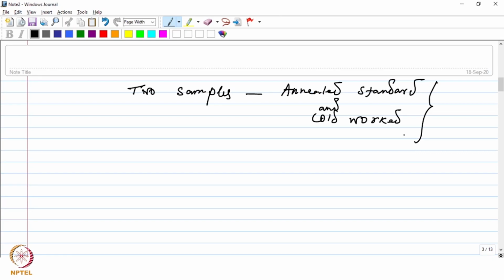Okay. So if that can be measured, you can display this difference, and that will actually indicate that the strain energy is being released, because the power required to heat the cold worked sample to a particular temperature will be lower compared to what you need for the annealed sample, because as you start heating, the cold worked sample would release the strain energy. Okay. So that is how you can actually experimentally see this, and it can be displayed in a plot like this.